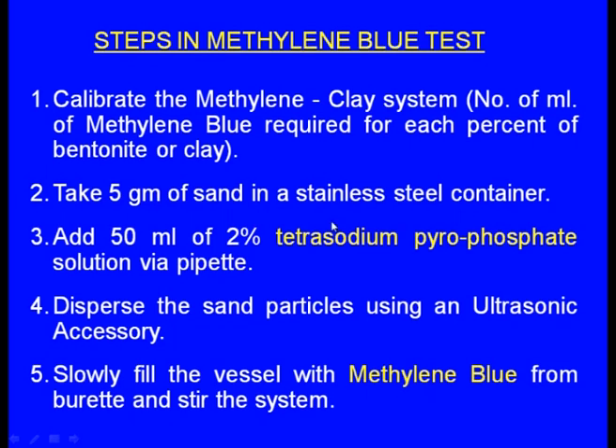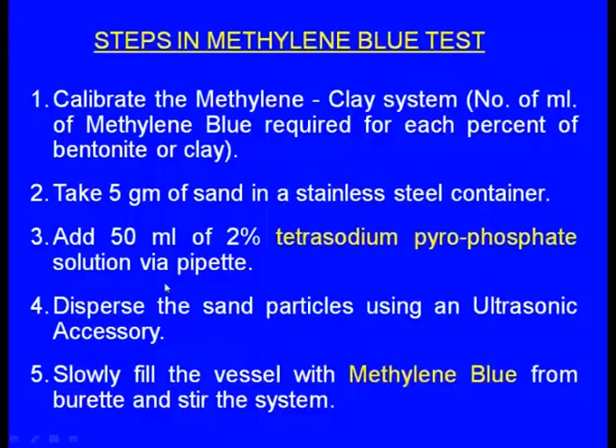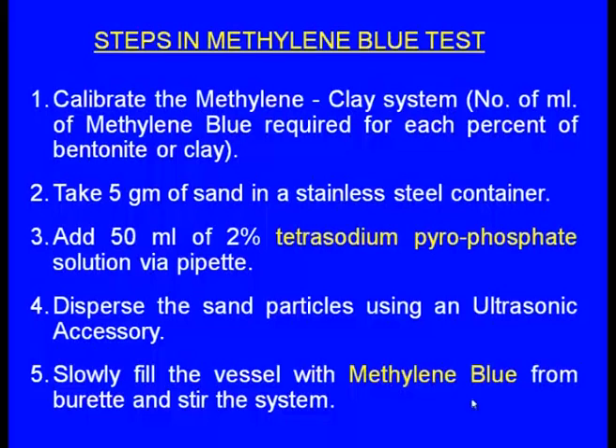In the second step: take 5 grams of sand in a stainless steel container. Add 50 ml of 2 percent tetrasodium pyrophosphate solution via pipette. Disperse the sand particles using an ultrasonic accessory. Then slowly fill the vessel with methylene blue from the burette and stir the system. We are dropping methylene blue drop by drop. The active clay in the sand readily reacts with the methylene blue solution — this process continues as long as active clay is present.